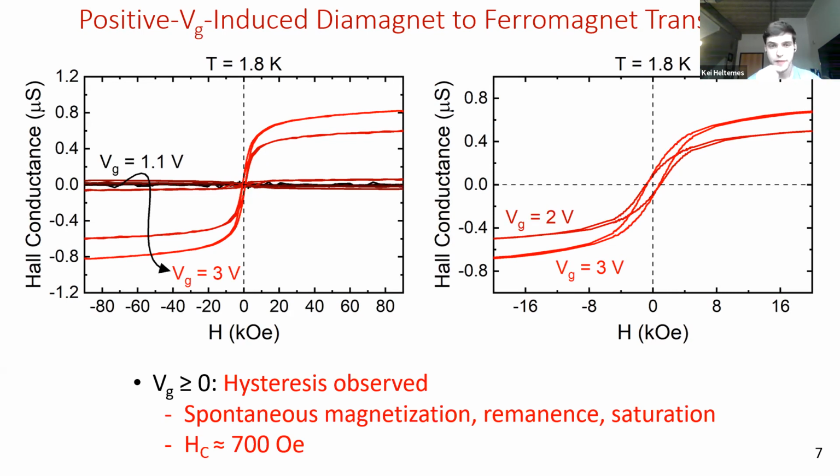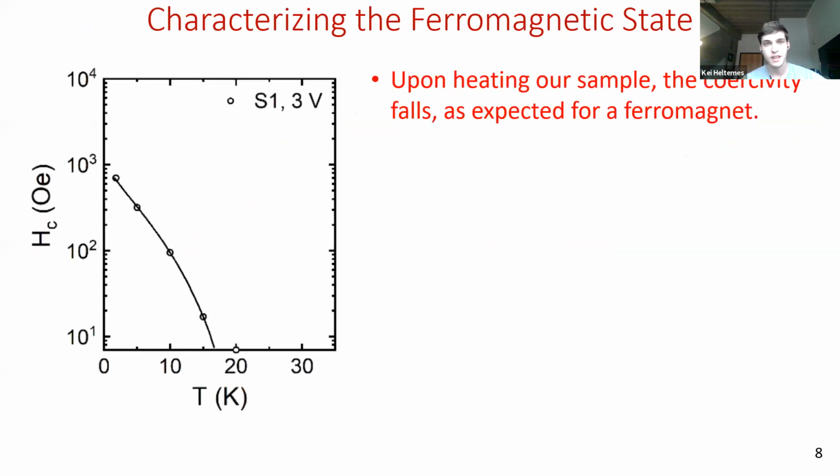One thing I want to note is that we're also seeing a positive Hall coefficient here in these high voltage applications. That's a very good sign because the bulk Hall coefficient in cobalt doped iron disulfide samples, magnetized samples, is actually positive. So it's exactly what we'd expect if we're actually causing this to turn into a ferromagnetic state like just adding cobalt atoms to our iron disulfide sample. So we could do some additional characterization here.